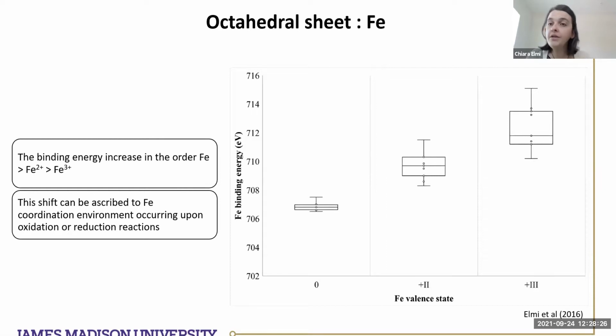Even for the iron, you know that the valence state of iron is 2+ and 3+. So even in this case, it's possible to distinguish the two components in the binding energy by the shift of the peak. The shift of this peak can give information about the reduction and oxidation state of the iron in the structure. And the binding energy from the metal iron increases based on the valence state of the iron itself, and that is based on the coordination of the iron in the structure.